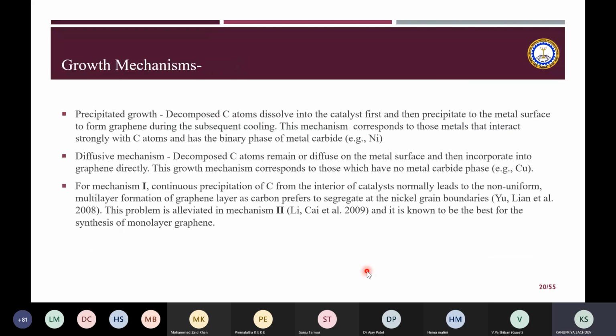So there are two mechanisms of the graphene growth on the substrate. One is the precipitated growth mechanism, which takes place when we have a substrate like nickel. Nickel has a tendency of forming a binary phase of metal carbide. In this case, the decomposed carbon atoms, which come from the precursor gas, dissolve into the catalyst first and then precipitate to the metal surface to form the graphene.